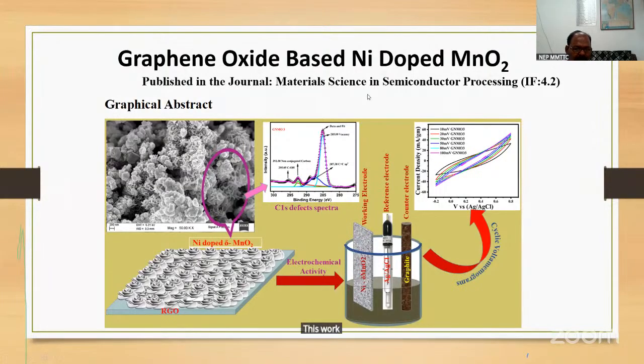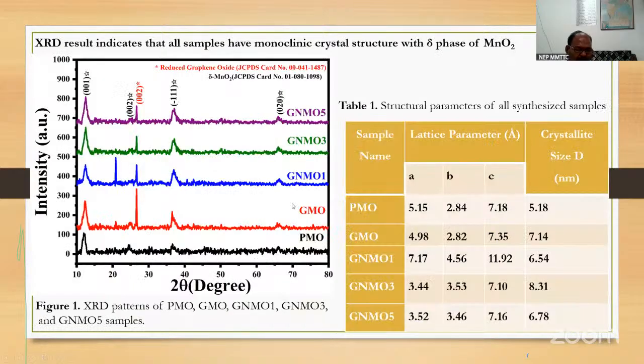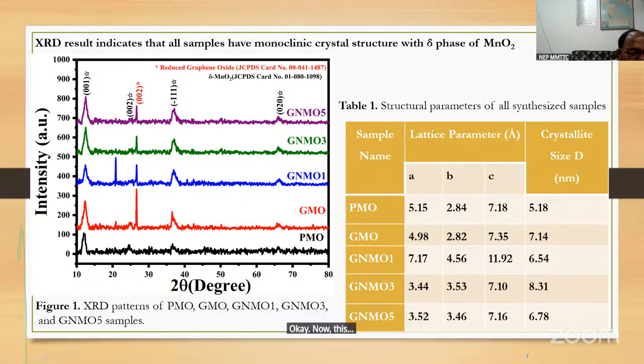This work was also published in Materials Science in Semiconductor Processing. Impact factor is 4.2. The graphene oxide based nickel doped MnO2 we synthesized, and we got this nickel doped delta MnO2. The XRD result indicates that all samples have a monoclinic crystal structure with the delta phase of MnO2.